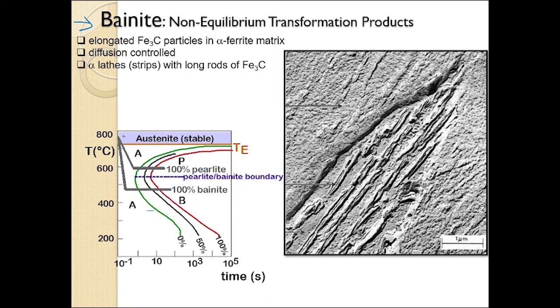So to get 100% bainite, the procedure is almost the same as pearlite, but we rapidly cool from austenite until a lower temperature, maybe around almost 500 degrees Celsius, and then we let it stay at that temperature for a certain time until we get 100% bainite. The other rules are the same. At the center line, it will form 50% austenite and 50% bainite. More than this red line over here, it will form 100% bainite.